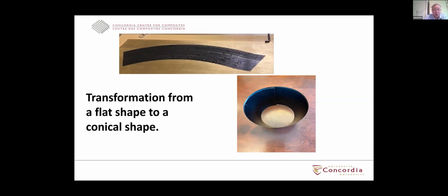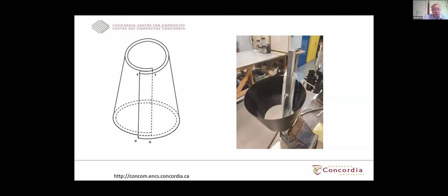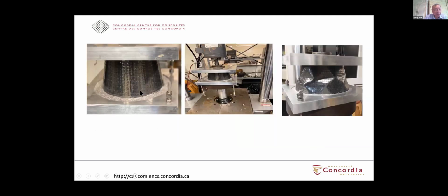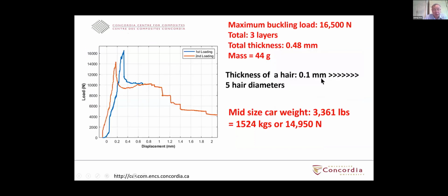So we can get the shape, but again, you wonder whether it can withstand a mechanical load, in terms of axial compression. So here we join the seam together using some adhesive, and then we subject it to mechanical load. We put it inside the MTS machine and load it up. You can see that under this kind of loading, it shows you the buckling mode. We load it 2 times, and it buckles. When you unload it, it recovers the shape again, and you load it again. This one shows the first loading, and this one shows the second loading.